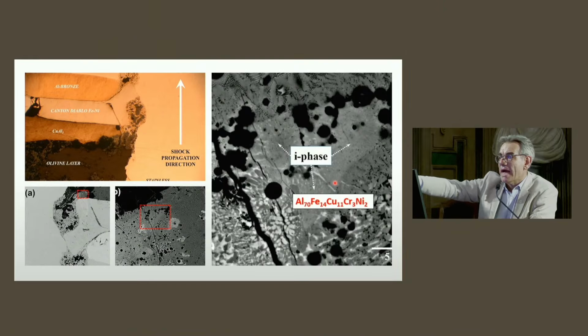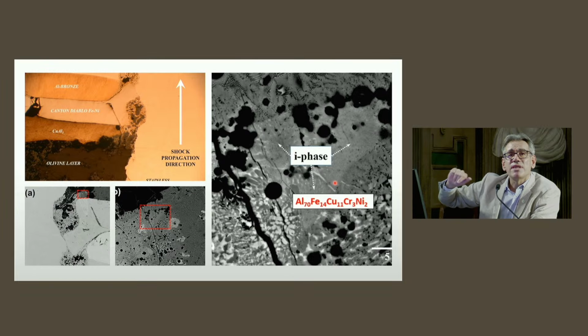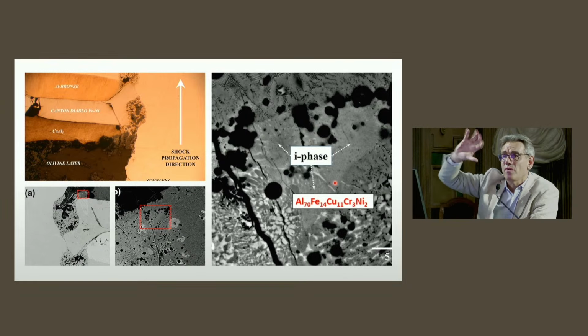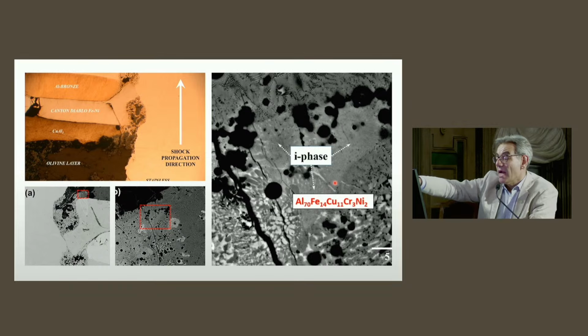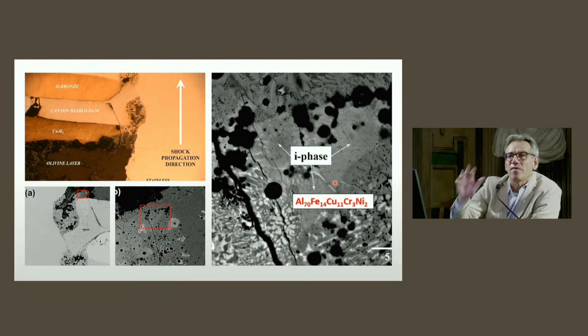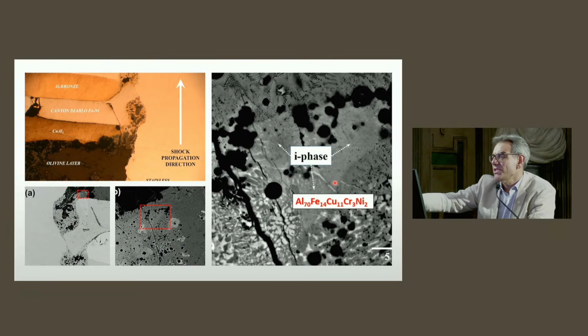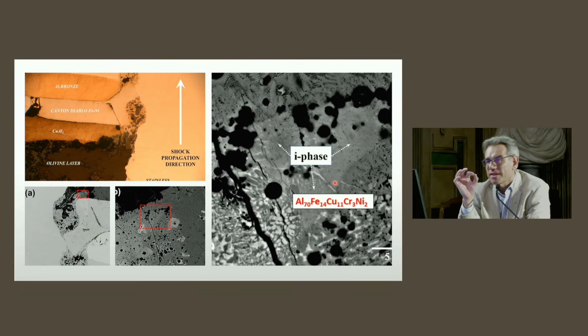We realized that the phase was actually icosahedral by means of field emission scanning electron microscope, electron backscatter diffraction, where we observed 5-fold symmetries. But since at that time we were used to verifying if the 5-fold symmetry distributions we observed with EBSD were actually real, I was able to extract a tiny grain, less than 10 microns in size, and carry out an X-ray single crystal diffraction study.